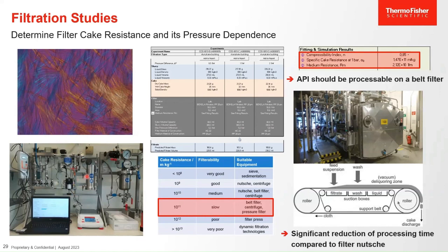In this particular study, the material was almost fiber-like, and we looked at filtration properties. This is our filtration equipment. It's a pressure filter. The filter actually sits underneath the vessel here. We fill our slurry into here. There's a bayonet that attaches the filter. We can use appropriate filter media that we use in manufacturing, we acquire the filtrate, and we measure the evolution of filtrate volume with time, and from that we can calculate the filter cake resistance. We support these activities with simulations.